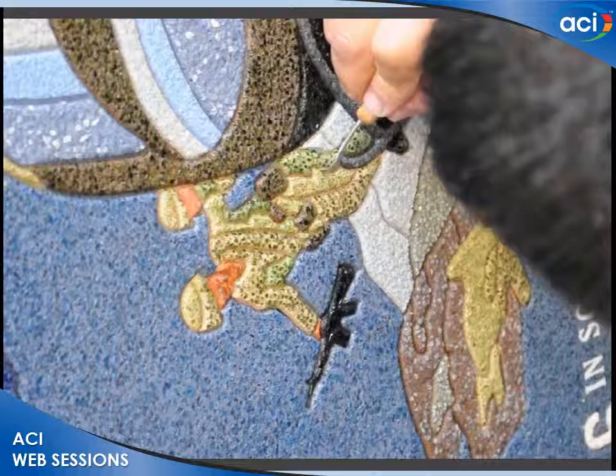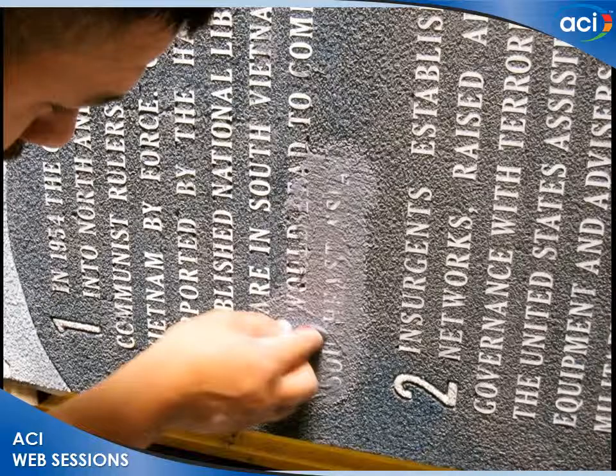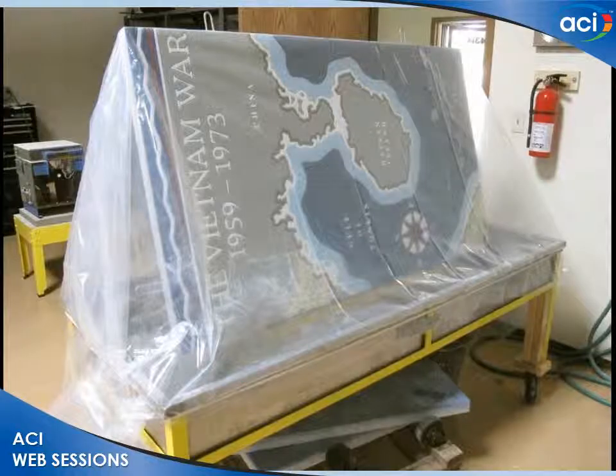We use dental tools to clean out the grooves. And just as Sid pointed out, the filling, the smearing to fill in the little holes. Well, we had a problem because some of the interior openings in the letters were just smaller than we could get a piece of glass in from the back. So we had to go through that same kind of smearing process with basically a mortar mix, the same as we had for the concrete.